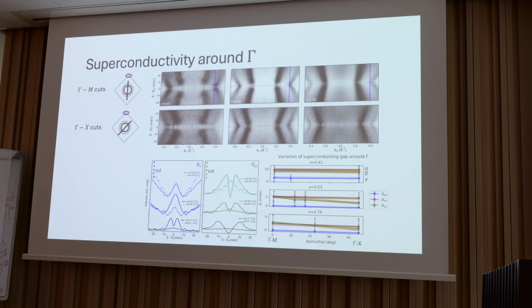So now we can look at superconductivity around gamma. The top row is these gamma to M cuts, and the second row is gamma to X cuts, and these are the 3 different superconducting hole doping levels. These are symmetrized spectra, and the green line indicates where the cut is taken for the YZ band, and the blue line indicates where the cut is taken for the XY band.